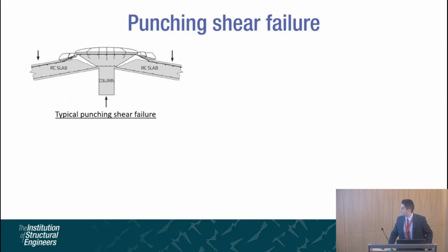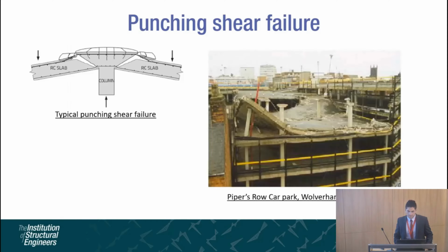In this failure mode, the slab collapses around a truncated cone over the column, which may eventually lead to progressive collapse of the entire building. This failure mode is often the governing failure criteria in flat slabs. On the right-hand side of the slide, we see failure of the Piper Row car park in Wolverhampton. The failure initially started by failure of one of the connections, and then it led to progressive failure of the